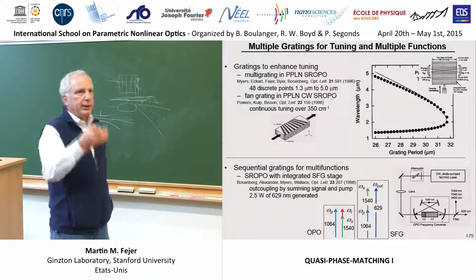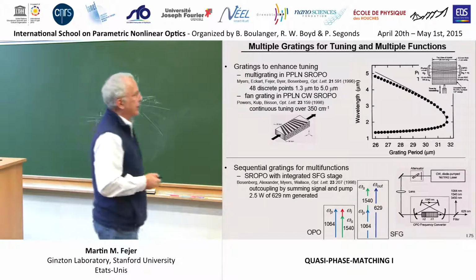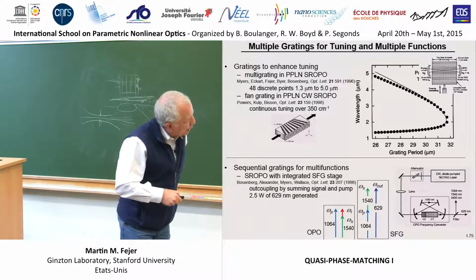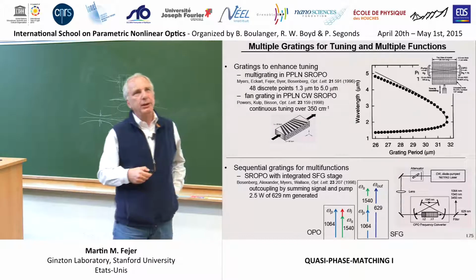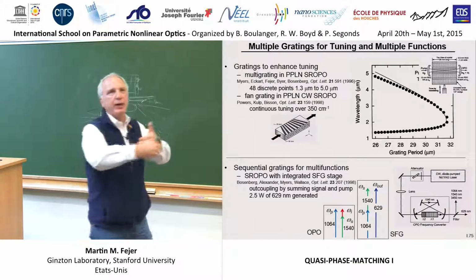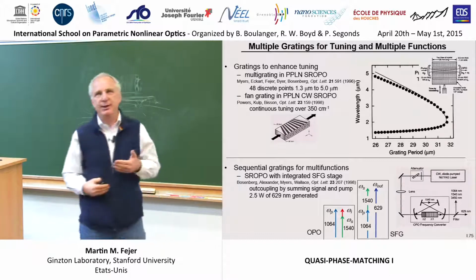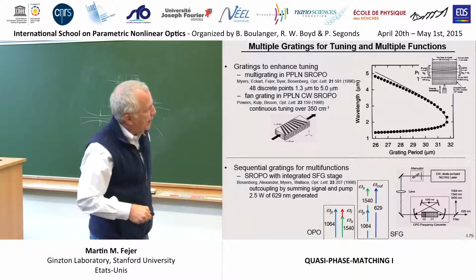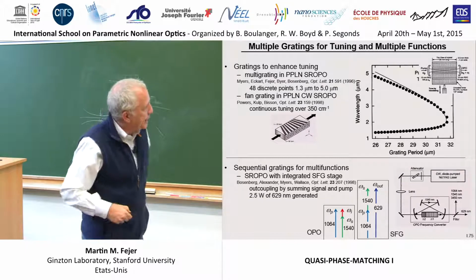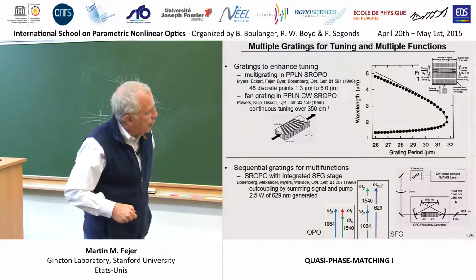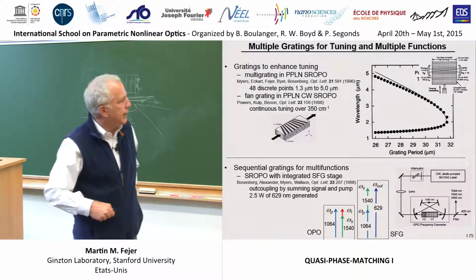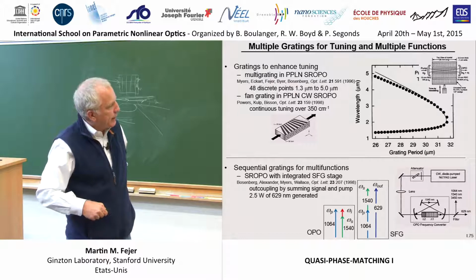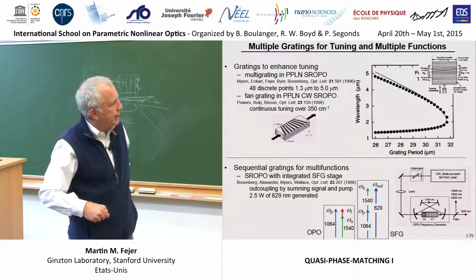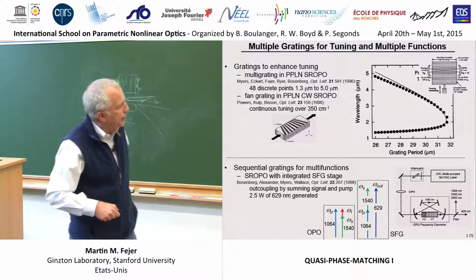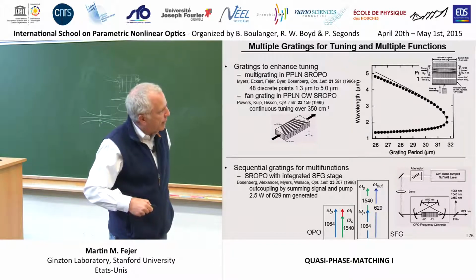Another thing you can do, and Majid talked about discrete versions of some of these things, is to put more than one grating in a crystal so that you can have serial operation of more than one nonlinear process. In this example from Lightwave Electronics, it's a 1 micron pumped OPO using one of these gratings, the longer grating. So the 1 micron pump and a resonated 1.5 micron signal wave plus an idler out at 3 microns. That's the basic OPO that you've got operating.